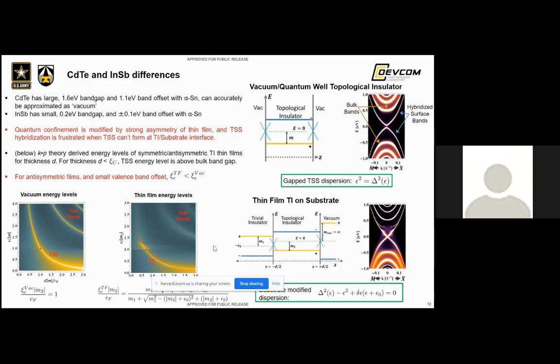So Patrick, Christina has a follow-up question. She asks, so alpha tin does not like to get transferred to other substrates after the fact either? Right, that's correct. Unless you can lock down your substrate, and then it's very stable on certain substrates. The substrates that we know it's stable on are the indium antimonide and the CdTe substrates. You can make those substrates thin, but to actually remove it and then put it onto a different substrate is somewhat problematic, I would say.